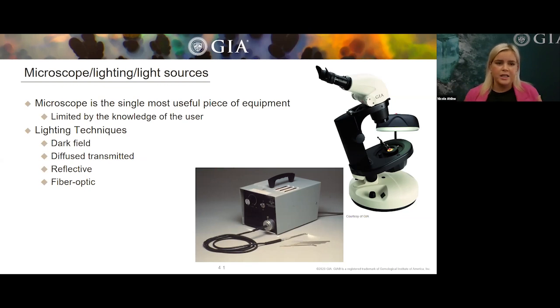And so under the lighting techniques, we have dark field, and dark field is when light is transmitted from below, and then it's actually being blocked by an opaque shield that's commonly black. And so the light is actually coming in from the sides. And if inclusions are present within your stone, those inclusions will appear nice and bright on a dark background. And this works best if the stone is transparent to translucent.